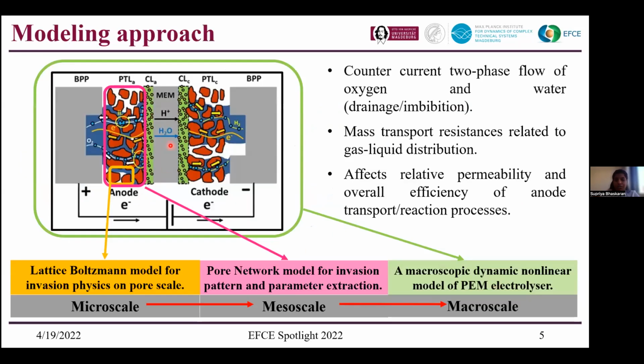Why is the anode porous transport layer the main focus? Because the anode porous transport layer has a complex process. We have the flow of water supplied to the catalyst layer, and we also have the removal of oxygen. This countercurrent two-phase flow occurring in the porous transport layer makes it more complex, and also gives a mass transport resistance to the flow of water as well as oxygen. So this automatically affects the overall efficiency of the anode transport and the reaction process.